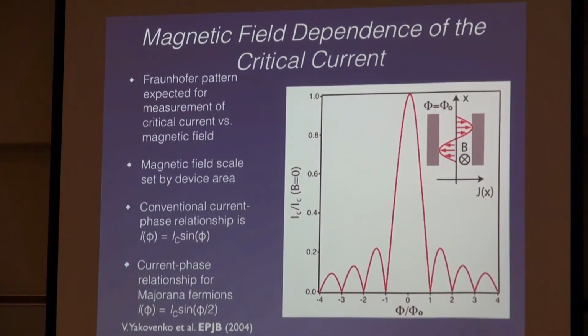The other came about when we started applying magnetic fields and looking at the response of the Josephson junction. Typically what you see is something that looks like this. As you pass a single flux through the area of the device, because of the Aharonov-Bohm phase you get around here, you can actually cancel out the supercurrent. And so you see this Fraunhofer pattern. The scale of the Fraunhofer pattern is set by the device area. The device area is just the distance between 2 leads plus how much on each side the magnetic field penetrates the superconductor. And this Fraunhofer pattern arises when you have this conventional current phase, the Josephson relation.